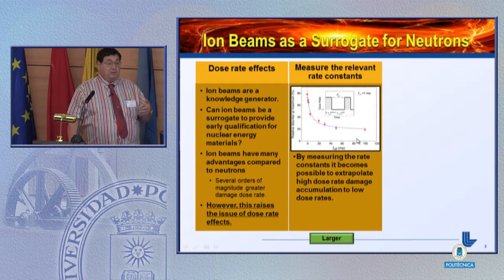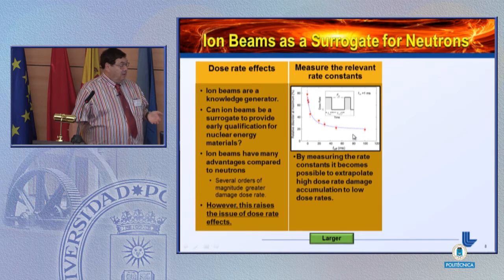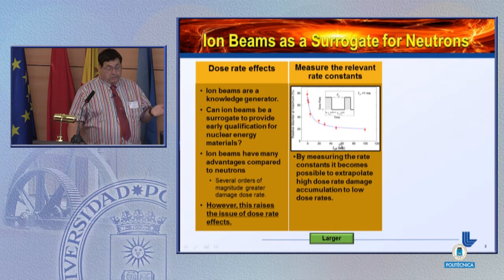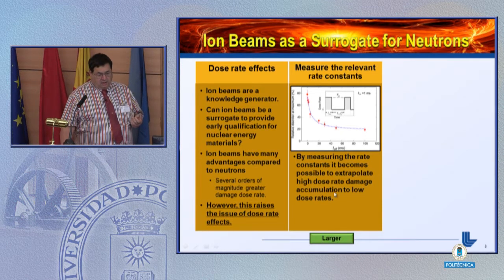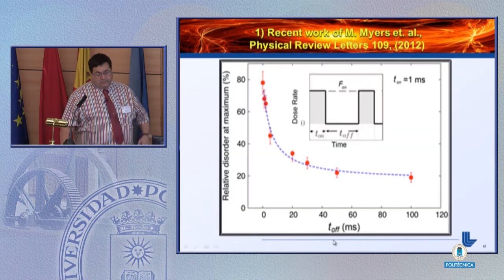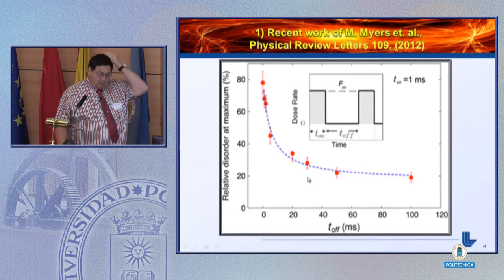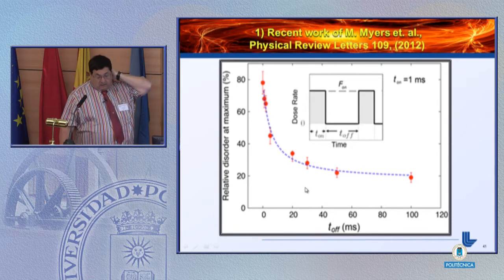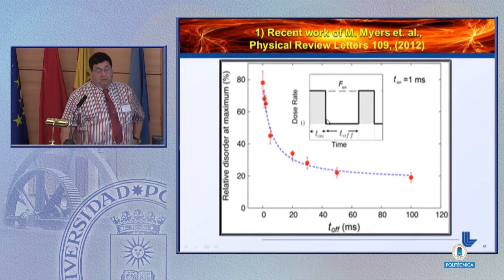So now I'm going to talk about a material that you're not going to build a reactor out of, silicon. A colleague of mine did a very interesting experiment at Livermore, and when I saw it, my first reaction was, why didn't I think about this? What he did is shown here, and I'm going to explain it to you. He irradiated single crystals of silicon with argon ions, so that's a fairly heavy ion. But he did this with a pulsed beam. The beam on time was 1 millisecond, and this is about 10,000 pulses. The thing that was varied in the experiment was the time between the pulses, the T off. So the period was being varied.